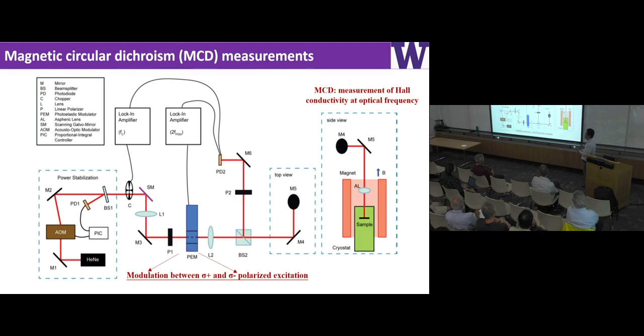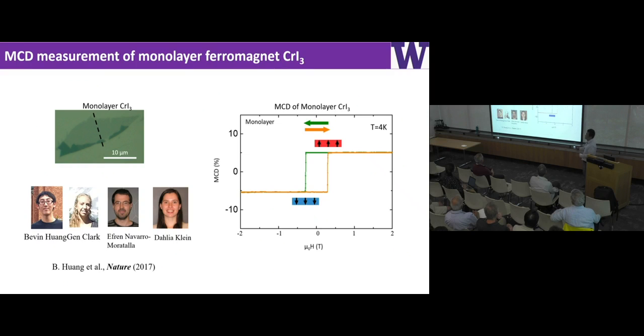We're basically sending a laser beam and modulating it between right circular and left circular polarizations. Then we send this polarization-modulated light to a sample. We measure the reflection difference between left and right circular polarization. So we call it MCD, which is magnetic circular dichroism. If you're not familiar with MCD measurements, you can think of it as a measurement of Hall conductivity, but at optical frequencies. Okay? So that's all I'm going to tell you. Then we're going to use this MCD technique. Here, just one example of what the signal looks like.